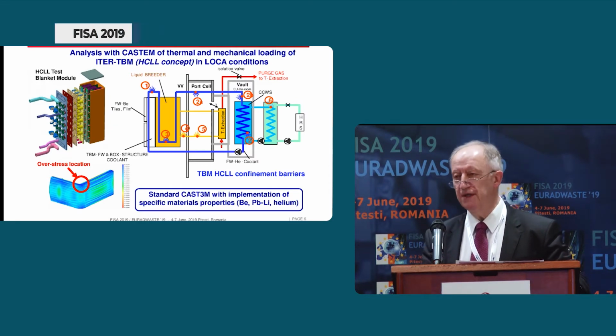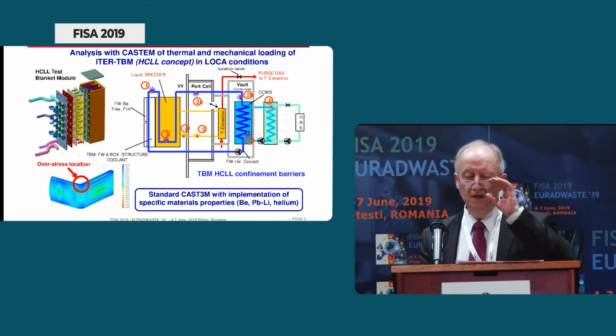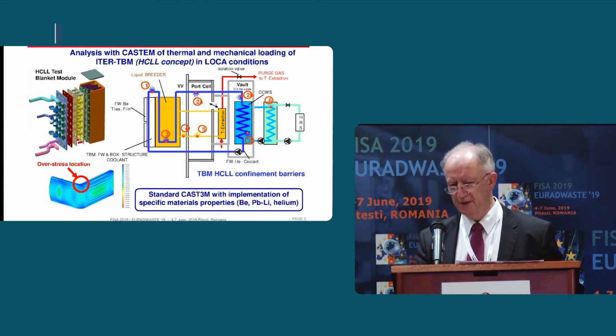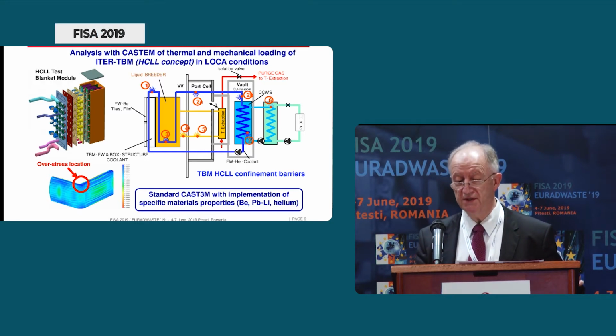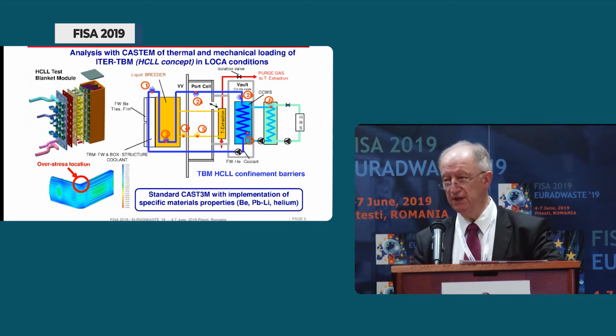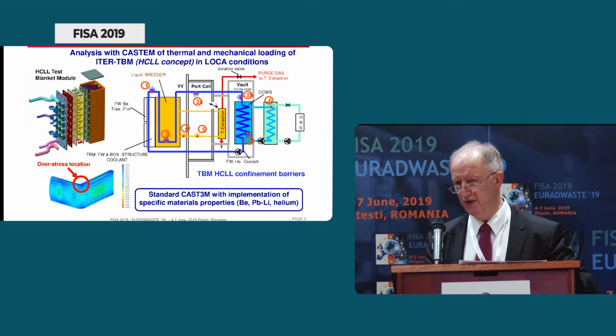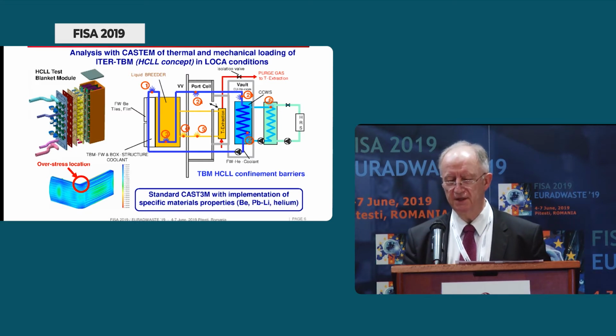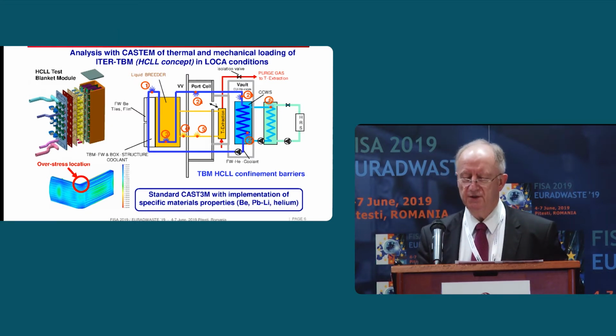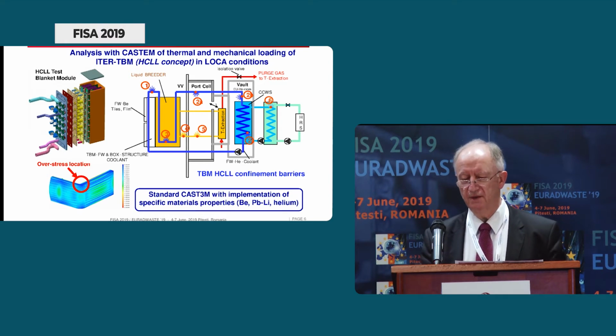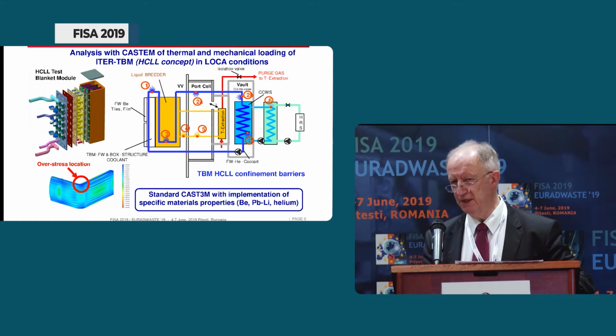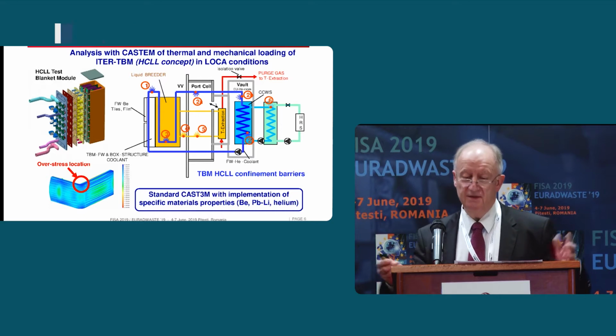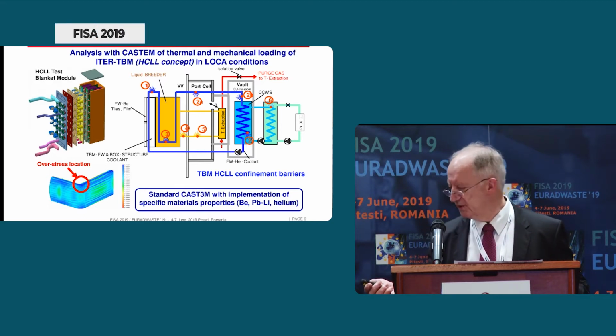Radioactive material should be contained in three barriers, like for fission reactors. Certainly for tritium, the first barrier is the blanket, the second barrier is the vacuum vessel, and provision could be made in the vault that supports the vacuum vessel and the magnetic coils, so as to achieve the confinement of the third barrier. Also, a radiological barrier should be achieved by appropriate shielding for neutrons and gamma. And this is another commonality with fission reactors.